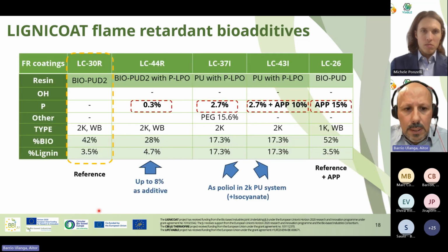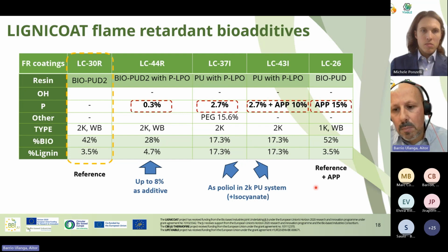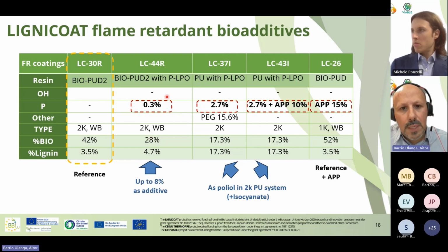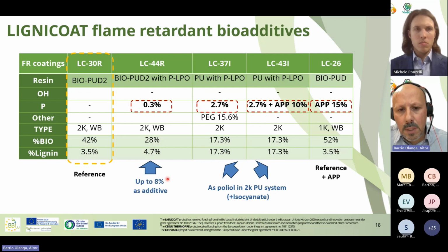These developments are currently ongoing, but we prepared different formulations. We used a reference formulation based on a polyurethane alkyd dispersion based on lignin, as commented in my introduction. For comparison, we have a typical system based on APP, a commercial ammonium polyphosphate, which is a commercial fire retardant. We prepared the lignin phosphate as an additive, but in this case we had problems and only reached 8% of additive, so we only reached 0.3% of phosphorus, which is very low. And we decided to move to increase the lignin content and also the fire retardant content.